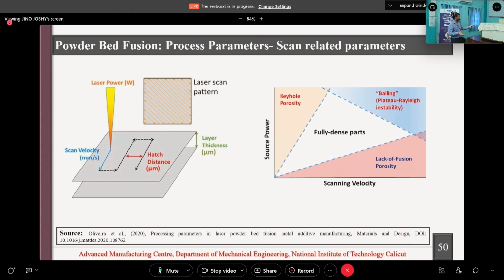And here you can see the interactions between the scan velocity as well as the power of the laser, the source power. If you are doing it in this region, that means scan velocity is less and the source power is in this region, you will end up with a keyhole porosity. Keyhole means your laser will be penetrating too much into your powder bed. That means it will be reflected inside your melt pool. The laser beam can get reflected inside and it will be reaching a higher depth than your layer thickness. So it will result in a keyhole melting. That means it will be going deeper and getting melted.